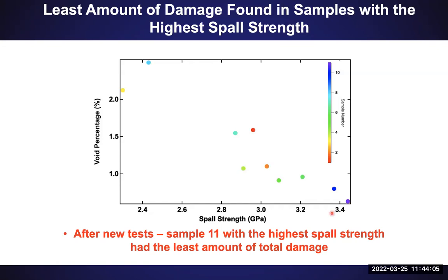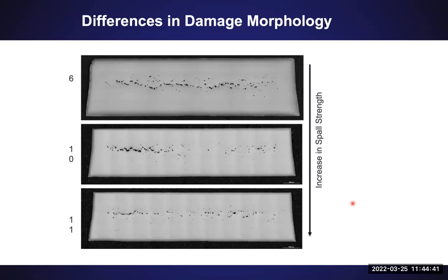I'd like for you to focus on these 3 points on the bottom right side of the plot. The 2 purple points are sample 10 and sample 11 that we had requested from the university, and they did indeed have a higher Spall strength and a lower void percentage. One thing that was interesting to us is that sample 11, which was built using the build parameters recommended by the manufacturer, actually ended up having the highest Spall strength and the least amount of total damage in the material. If we compare sample 6, 10, and 11, so these are the samples with the highest Spall strength,